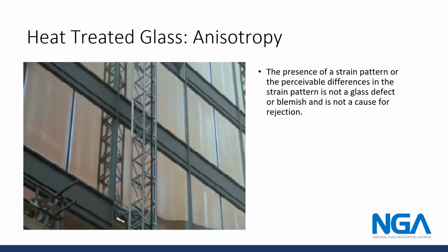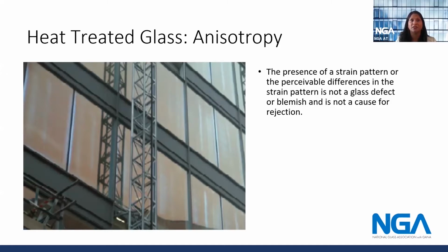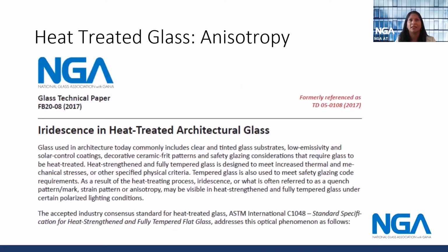So because it's the way you're able to capture the stresses into the glass, that's why it's always going to be inherent in the process. It's a characteristic of all heat treated glass. And it should not be mistaken as discoloration or non-uniformity of the tint or the color, and it's not a defect in the glass. The strain pattern does not affect the physical properties or the performance values of the glass itself either. In addition, NGA has a document on the iridescence in heat-treated architectural glass that discusses this phenomenon, as well as goes through the different standards that talk about the viewing conditions and what's acceptable and what's not.